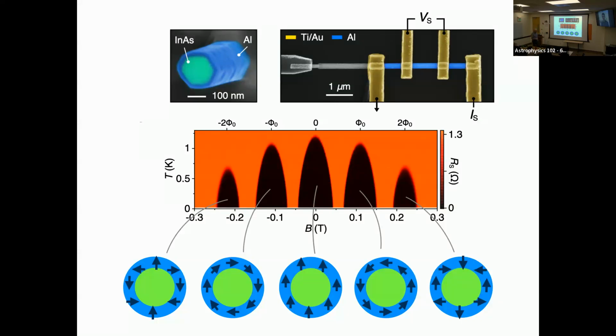And if you look at this diagram, you can get a sense of what I mean by the superconducting phase evolving as you go around in a circle. So here it is evolving by 2 pi within this first lobe. Here it is evolving by 4 pi within the second lobe, minus 2 pi, minus 4 pi, as it evolves in each of these lobes, making this new low energy ground state. But if you're halfway in between, the currents that are used to generate the flux expulsion exceed the critical current of the superconductor itself, killing superconductivity.